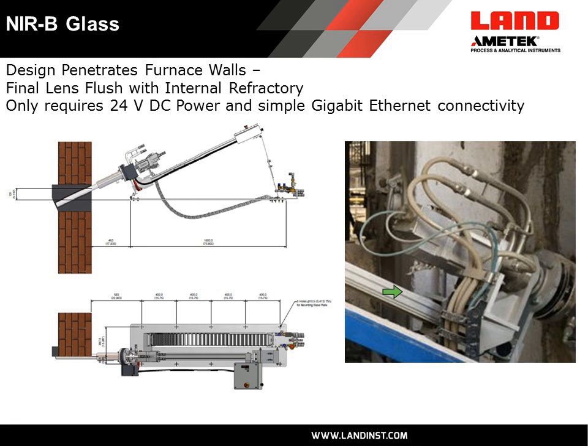On this side, we see a photograph of a unit actually installed, again at this angle looking downwards, and it's installed on an optional auto retraction mechanism. That auto retraction mechanism will sense if there's a loss of coolant to the system or a loss of purge air or an over temperature situation at the lens tip. Okay, and on any of those conditions, that auto retract system will automatically pull out the imager to prevent damage, and as that imager retracts, there is a shutter which closes the port.